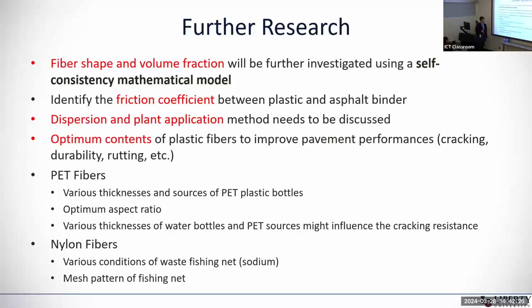And for PET fibers, we used only one source of plastic bottles, which is Deer Park water. It has a thickness of 0.28 millimeter. But if you use different types of water bottles, you might find them a little bit thicker. So we try to use different types of plastic bottles in this asphalt. And for the optimum nylon fibers, as I said, different types of fishing net have different mesh patterns. We try to figure out the different mesh patterns, use them in the asphalt plant, and see how the mesh pattern affects the cracking resistance improvement in our research.